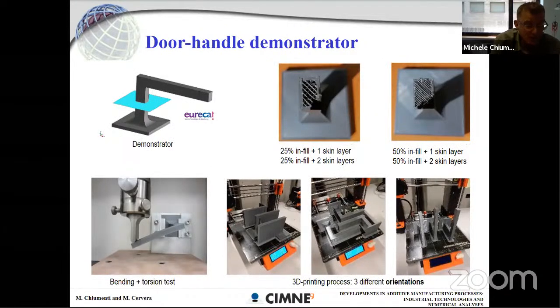Once you have the homogenization of the lattice structure and you have the material characterization of the contour, we went through different demonstrators to validate our software. I will just show you one of them that we did with the help of Eurecat. This is a door handle demonstrator, and it is being printed in 3 different orientations and loaded. Observe that this is quite a difficult test, in fact, because it includes both bending and torsion tests.